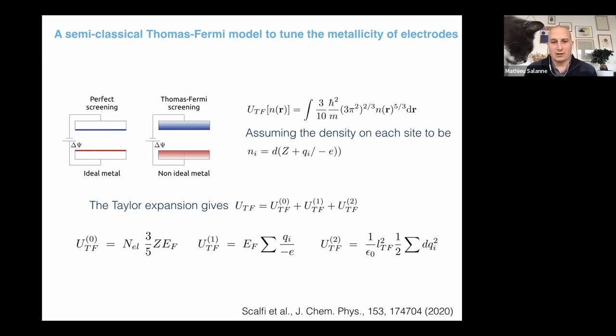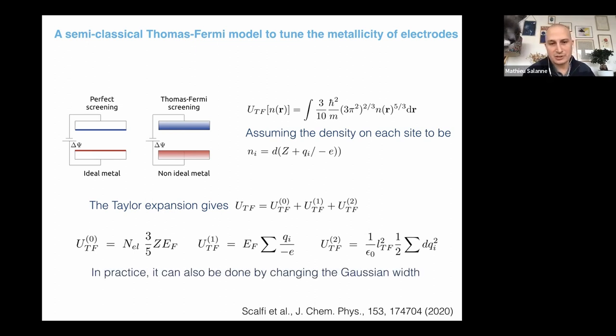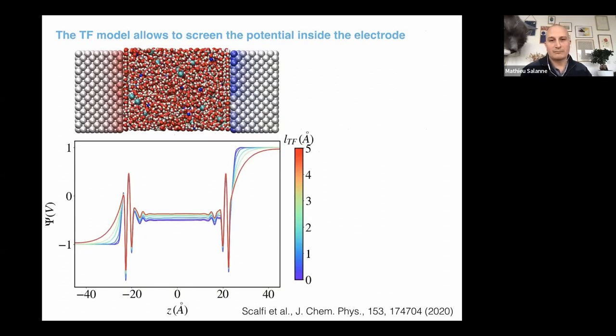And you see that here, the first term is just a constant that you don't care about. The second one involves the Fermi energy of the material. But if you have the same material on the two sides, it will cancel out, so you don't have to care about it anymore. And the most important one is the third term, which is quadratic in the charges. And it depends on a quantity, the Thomas-Fermi length, which measures the screening inside the electrode. And then by looking at the equations and comparing them with the equations we were using before, we could see that in fact, this was already a bit included in the model by Michiel, because there is a Gaussian width that is also impacting the second order term of the charges. So there was already a bit of this ingredient taken into account, but we never changed it in previous simulations. So now what happens when we include this explicitly?